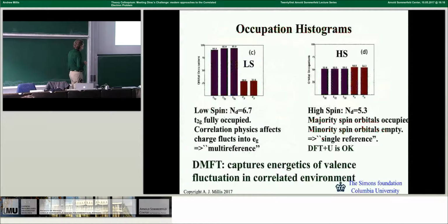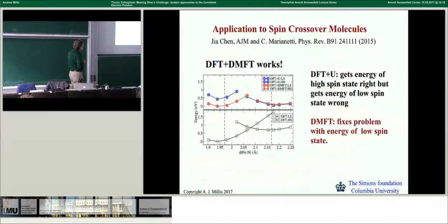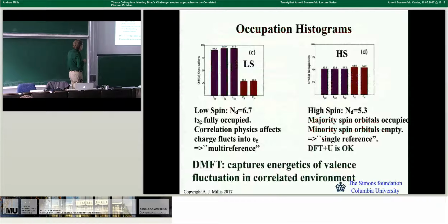All right? Now it's interesting to look at what's really happening. If I look at the two states, the high spin state, where we get essentially the same answer as DFT plus U, and the low spin state, what you see here is essentially the density matrix projected onto the iron site. In the high spin state, the iron just has a half-filled D shell. It's electrically inert. In chemistry language, it's single reference. Density functional plus U is okay.